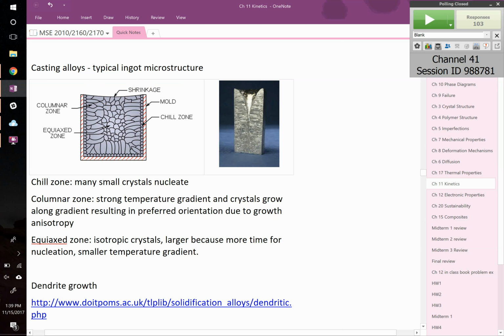And then if you were to cut that thing open and polish it, you'll notice that the microstructure is also changing, right? You have a bunch of really tiny grains here at the very edge. Then you've got these long grains in the middle region, and then you've got equiaxed grains, which are not stretching in any one direction, in the middle, right? This happens because you have a temperature gradient across your sample as it's cooling down. So you see lots of nucleation happening at these edges. How come? Why do you see tons of nucleation right at the edge of the mold?